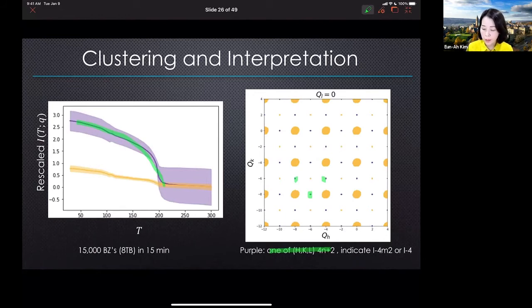And what this says is that these peaks that were suppressed in the high temperature phase have now become allowed with the lower symmetry at temperatures below 200 Kelvin. Based on this selection rule, we can already rule out all other possibilities other than these two structural possibilities. The first one would lead to a two-dimensional order parameter, and the second one would have given us a first order transition. So the fact that this order parameter behavior looks very second order like is already a strong indication that out of these two, the first one is more likely.